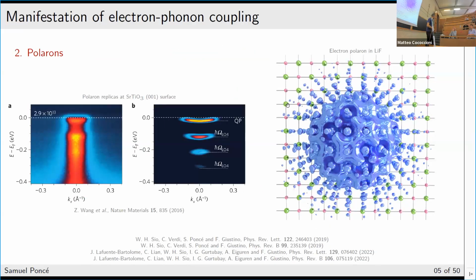If you are in materials where you have a very strong electron-phonon coupling, or you are at the band edge, then again, using this ARPES technique, you will see the appearance of satellites or band replicas. You can notice that they are split by typically an optical phonon energy from each other. Those are signatures of large polarons. Recently, tools have been developed to describe these large polarons using only the information on the primitive cell.